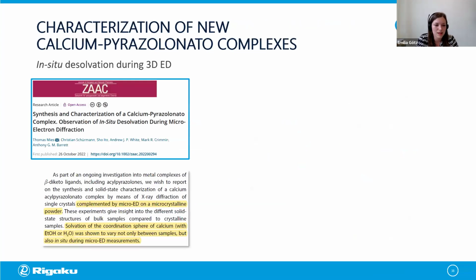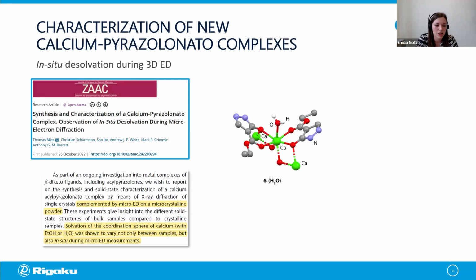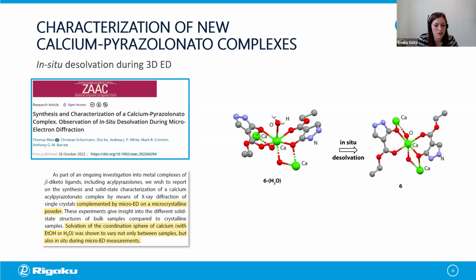Interestingly, sometimes the change in the crystal structure is even visible in situ in the instrument, like it was in this paper by Mies et al. about the characterization of new calcium pyrazolonato complexes. And here a desolvation of the coordination sphere of calcium was seen during the measurements. So first, the structure of the calcium complex with water could be determined, and then an in situ desolvation could be observed where the water was lost from the calcium complex and this structure was formed.